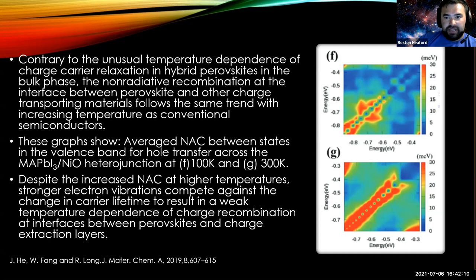So despite the unusual temperature dependence of the charge carrier relaxation in perovskites in bulk phase, the non-radiative recombination at the interface between a perovskite and another charge transporting material follows the typical trend that you see in other semiconductors. So the non-adiabatic coupling increases as temperature increases at the junction. But despite the increase in non-adiabatic coupling, stronger electron vibrations were shown to compete against the change in carrier lifetime, and it results in a relatively weak temperature dependence, but still influenced by temperature.